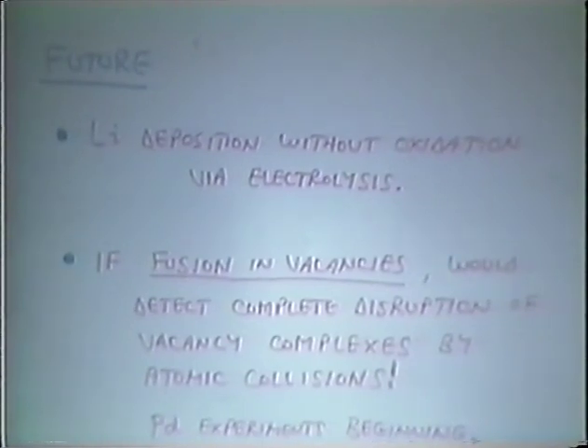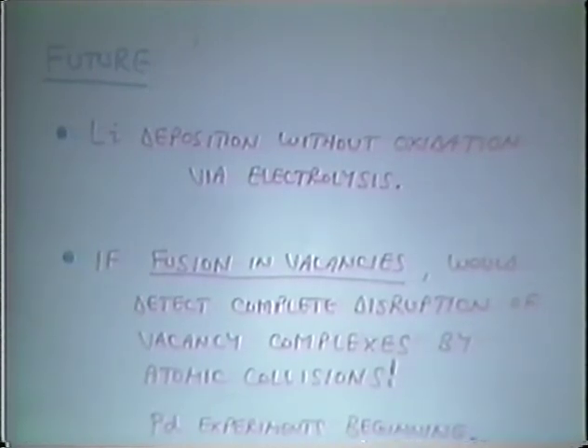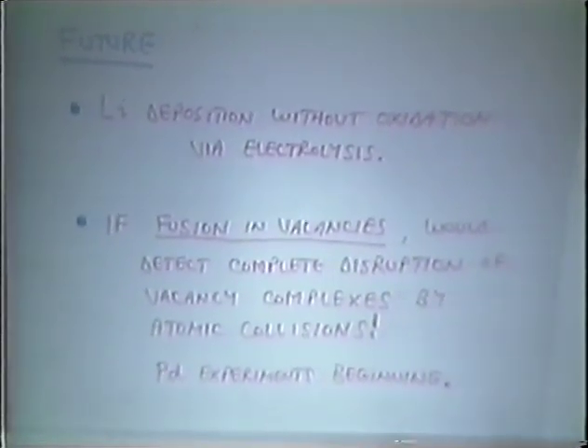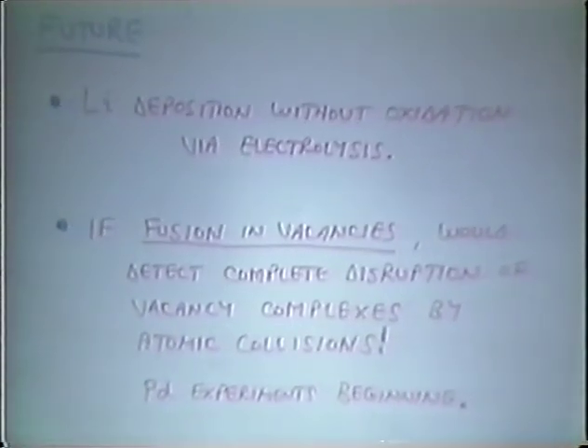we realize that we may be able, in certain cases, to use this technique to deposit lithium in an unoxidized form on metals, and perhaps to introduce it for purposes of diffusion. Now, finally, if fusion were to take place in lattice vacancies, for example, by pressing many atoms into a vacancy, we would then be able to detect the complete disruption of the vacancy complex after the fusion event, because the atomic collisions would knock atoms out as they're exiting in opposite directions. And we're just now beginning experiments to study vacancies and hydrogen trapping in palladium. Thank you.